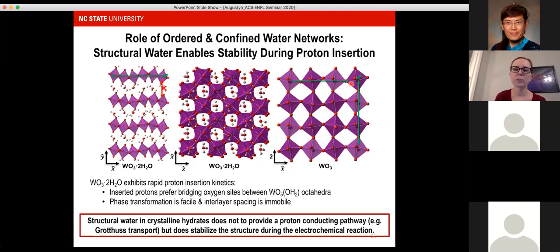And so as a result, you just have much more structural change taking place for each electron that's injected. So the structural water in these crystalline hydrates does not seem to provide a proton conducting pathway, which was our original hypothesis, but does stabilize the structure during the electrochemical reaction.